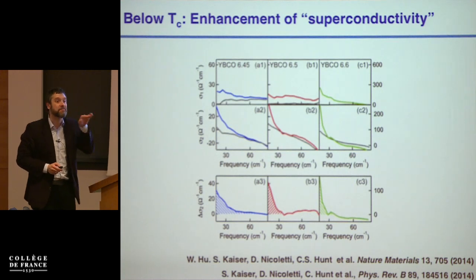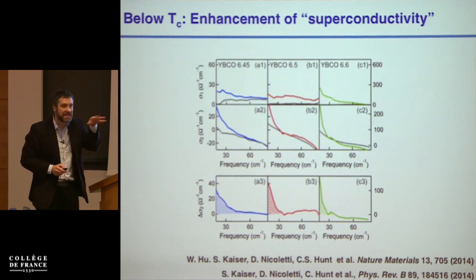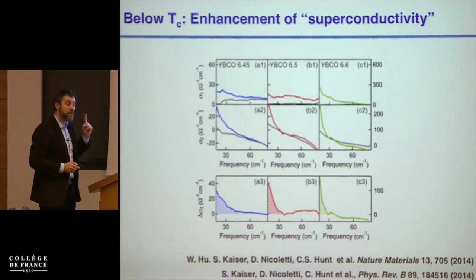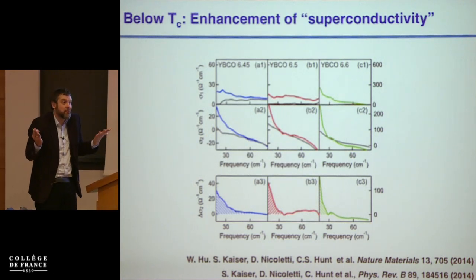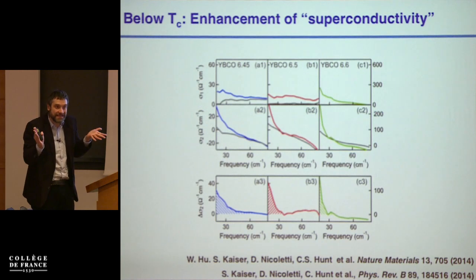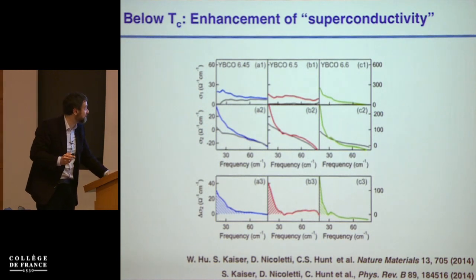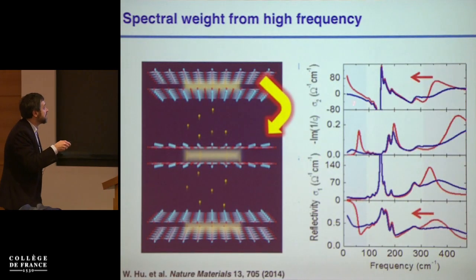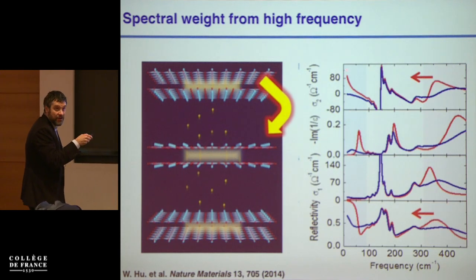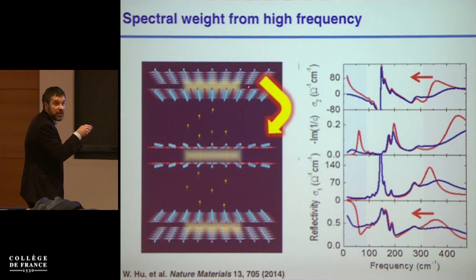As a matter of fact, the system becomes slightly more resistive in the planes, but it stays broadly the same. So in principle, this means that the number of Cooper pairs has to be approximately the same. Okay? What W. Hu has found in this paper is that all the spectral weight that you gain here comes from a redshift of the spectral weight of the second junction.